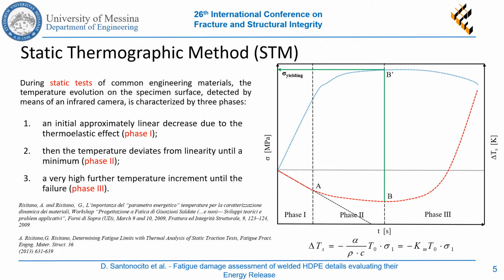If it is possible to estimate the stress at which the temperature trend deviates from linearity, that stress could be related to a critical macro stress which is able to produce in the material irreversible microplasticity. This critical stress is the same stress that, if cyclically applied to the material, will increase the microplastic area up to produce microcracks, hence fatigue failure.